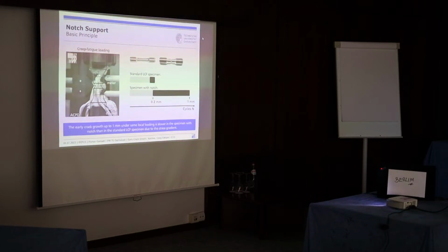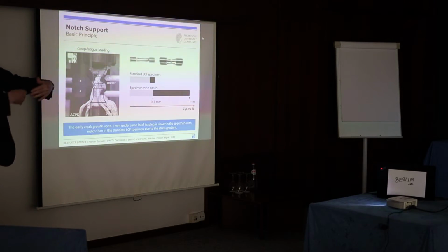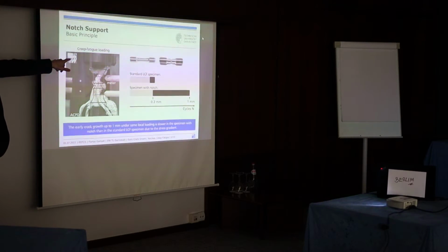Our basic principle to do so is at first an experimental determination or quantification of this effect. So what I already said is we would like to determine the number of cycles to crack initiation, and here we need to define constant crack depths to deal with, and this is in our case 1 millimeter. And we investigated the number of cycles up to 1 millimeter with different kinds of specimen geometries.